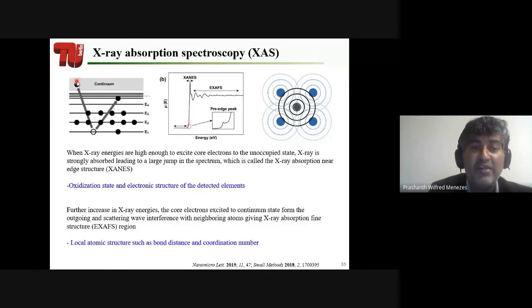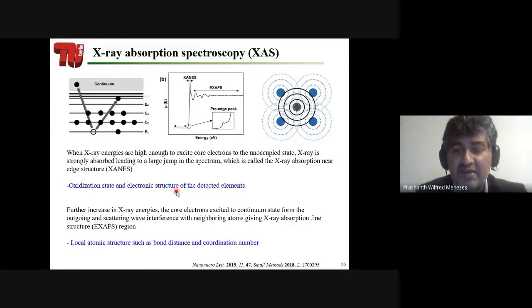And then if you apply more energy, you are kicking out this electron to the continuum. When this electron goes out of the system, it interacts with other atoms, and then you would get an interference. And this interference pattern is just shown here. This region is called the EXAFS region, the X-ray absorption fine structure. From this spectra, we can understand the local atomic structure as well as the bond distance and coordination number. So it will give you some information which I'll show you in the next slide.